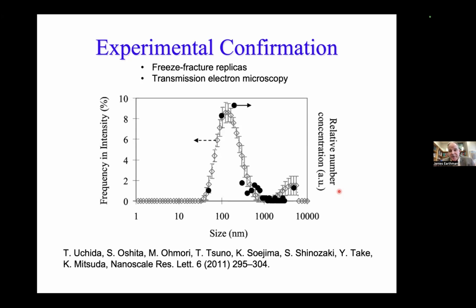And then the replicas are taken out, put in the transmission electron microscope, and whatever was inside that droplet is then observed in the transmission electron microscope. And so they measured these nanobubble sizes, these black circles, and the agreement was so good with the other data that I just showed you that they actually plotted that data as well.